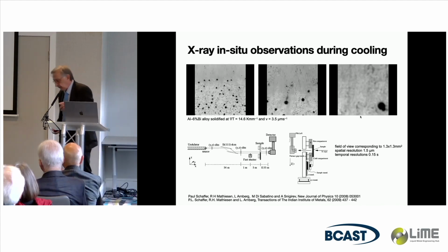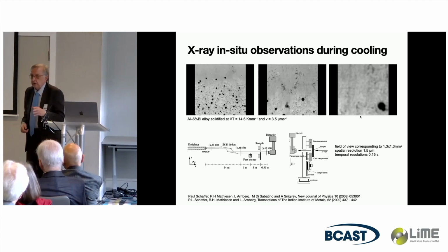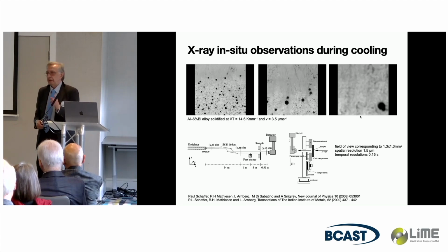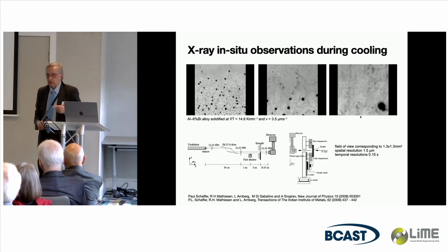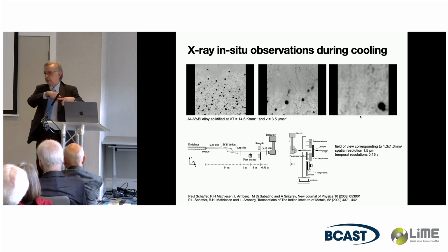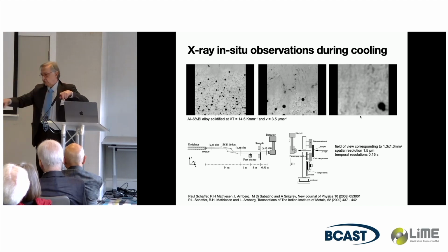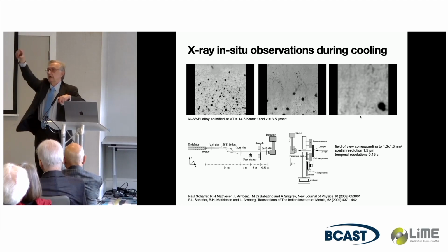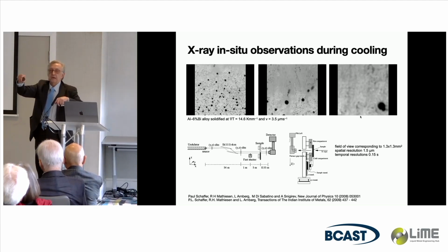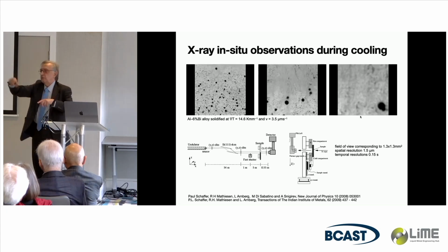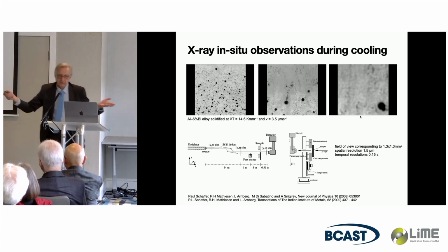And this is due to the fact that Stokes motion goes proportional to the square of the radius of a particle or a droplet. Marangoni motion is linear. So if you have a velocity as a function of radius, one is linear, the other is parabolic. If the droplets are small enough, Marangoni wins. If the droplets are too big, Stokes wins. That's very simple.